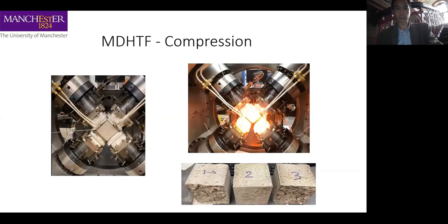So this is the first facility, where we're testing materials under compression in 3 directions or tension in 2 directions at high temperatures. So this is one commissioning test where we have concrete cubes, where you can see in here we have actuators from 2 directions. In this case, there is another set of actuators in the other direction, and the actuators are heating our specimen by induction heating. And you can see on the right-hand side, the red hot of the specimen. As I said, it can go up to about 1,000 degrees, and the loads can be in any combination in 3 different directions. So that's the compression test. Next slide, please, Joy.